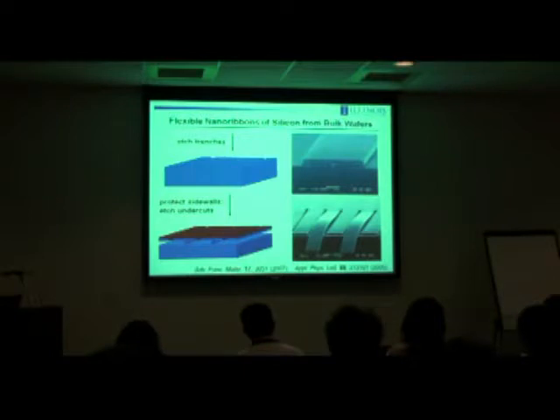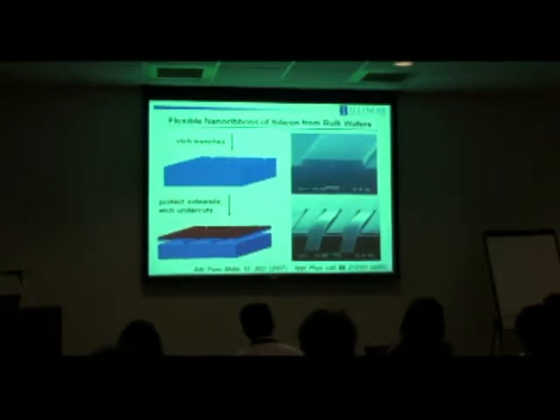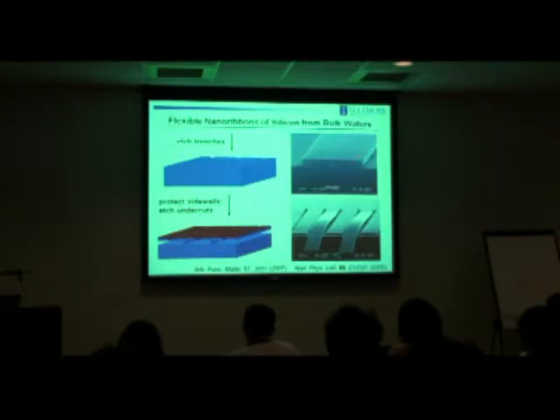You can take a commodity 111 silicon wafer. If you do a two-step etching process, which involves a vertical trench etch, followed by top surface sidewall passivation and an anisotropic undercut etch with a wet etchant like KOH, then you can slice off of the near surface region of the wafer very thin ribbons, wires, platelets, membranes of semiconductor grade silicon. And that's what's being shown here. This is a cross-sectional SEM view after this undercut etching has proceeded for a little while, but not completely undercut the ribbon, just to illustrate what's going on here. Typically, in a real process, we completely undercut. And in that kind of thickness range, 150 nanometers or so in this particular case, the silicon becomes quite floppy and bendable, just due to that elementary bending mechanics that I mentioned before.